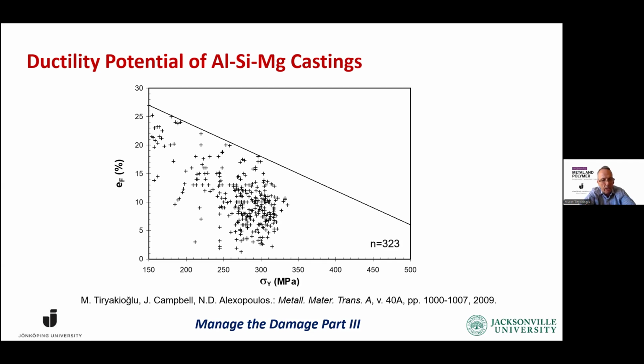We put all the data we could find on a scatter plot with yield strength on the x-axis and elongation on the y-axis. When we focus on the maximum numbers, you can see that there's a trend. We call this the ductility potential. For aluminum silicon castings, we can write this ductility potential as 36 minus 0.064 times yield strength, with yield strength in megapascals. That will give you a percentage. So at any given yield strength value, you can calculate a ductility potential of that alloy.